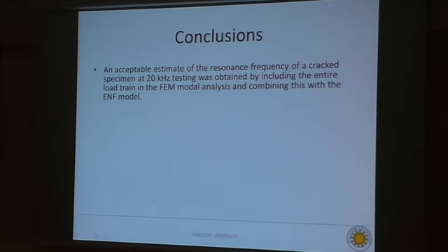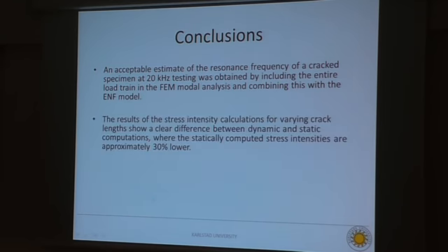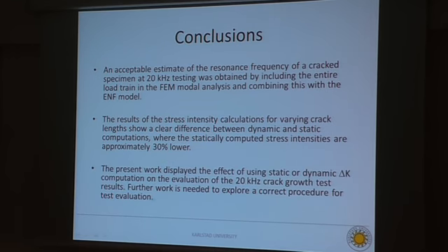The conclusions, I can conclude that we have an acceptable model for the frequency dependency on the crack lengths. And we also see a clear difference between the static and dynamic calculated stress intensities, but we can't really say, not yet at least, which one is the best one. We need further investigation to really conclude whether the statically calculated stress intensities are better or worse than the dynamically calculated stress intensities.